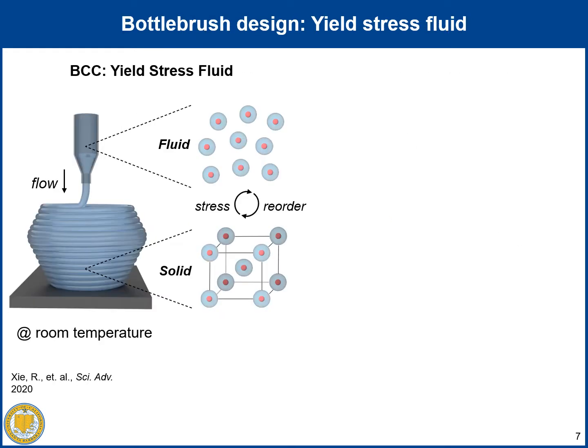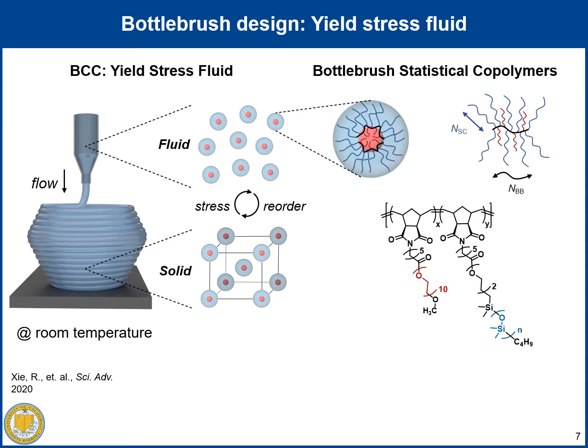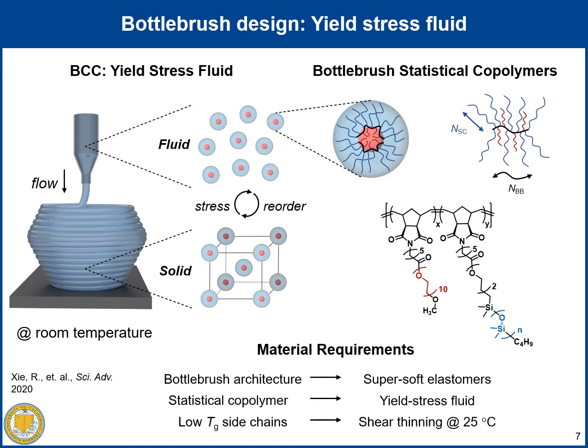Specifically, the yield stress fluid property is achieved through self-assembled body-centered cubic spheres, which are comprised of bottlebrush statistical copolymer of polyethylene oxide and polydimethylsiloxane. PEO is the core, while the PDMS is the majority component. Therefore, the key design requirement for room temperature 3D printing of super soft elastomer is bottlebrush statistical copolymers with low Tg side chains.